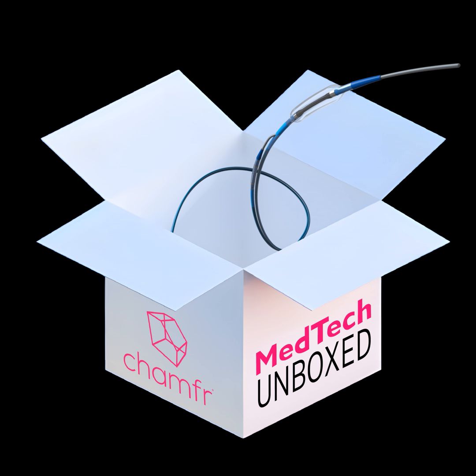And then depending on how thin your part is, it's going to take pressure to get through every last inch or fraction of an inch of your part. How much shrinkage you get is impacted by a lot of things, but one of the strongest variables is the pressure that a particular little slice of your part sees at the time that it freezes. So what we're trying to control, amongst other things, is keeping a constant pressure profile timed to the freezing of the part. Ideally we get a constant shrinkage rate.